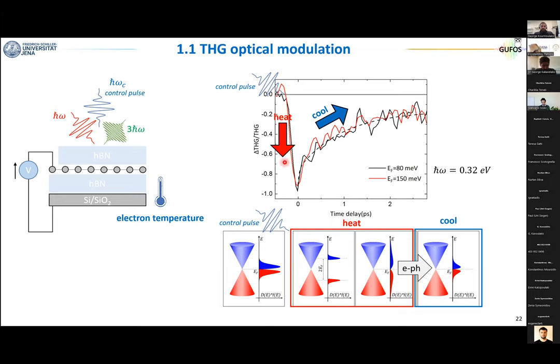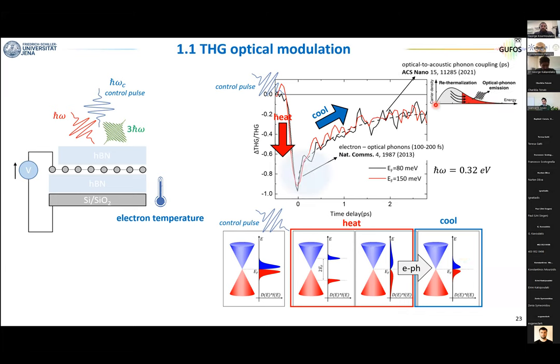Here you see there is a very rapid drop in the third harmonic efficiency, and then a certain recombination dynamics that takes something in the range of picoseconds. Now, this recombination dynamics represents this sequence of events that I was discussing before. And if you zoom in, you will recognize that there are mainly two dynamics at play. The first one is very fast, it takes approximately 100 femtoseconds. And this is typically attributed to this process here, the electron-phonon scattering, so the electrons that couple to the optical phonons of the material.